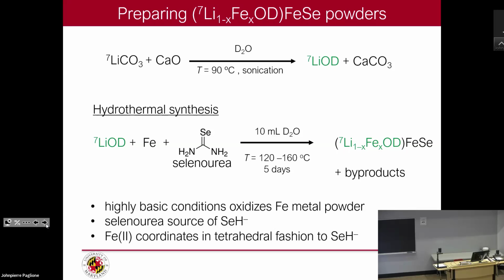In fact, you can see the volumes that you work with. And these are sort of an idea of your reagents that you want. For example, we use selenourea, pure iron metal, lithium deuteroxide that we make, and basically the amount of time. So for the hydrothermal practical, for example, you can't go in and get a crystal out the next day. It takes time. This one is 5 days, roughly, sometimes a week. And you can make this lithium iron deuteroxide. It turns out that we just found that D2O is different from H2O in the products that you get. D2O was much, much better to avoid iron oxides and other impurities like that. And so that was a very nice fortuitous discovery that we made.